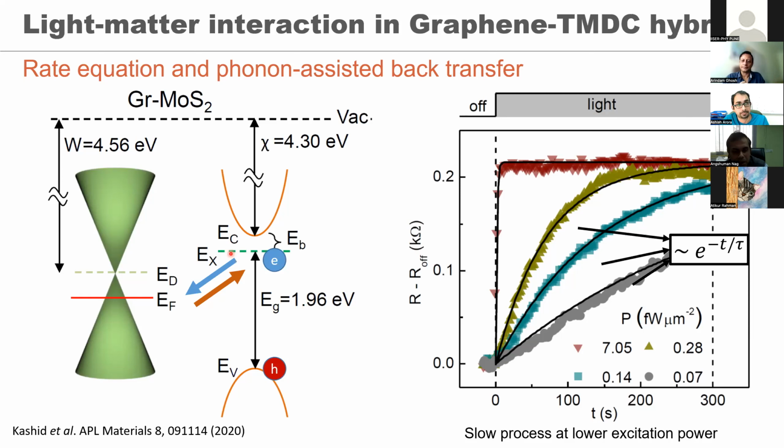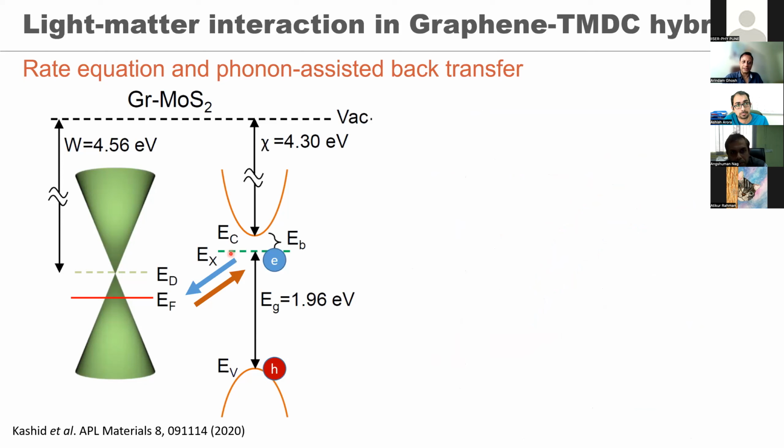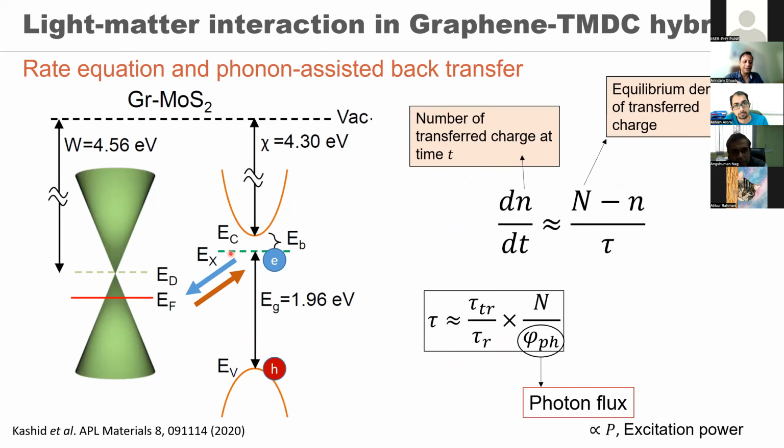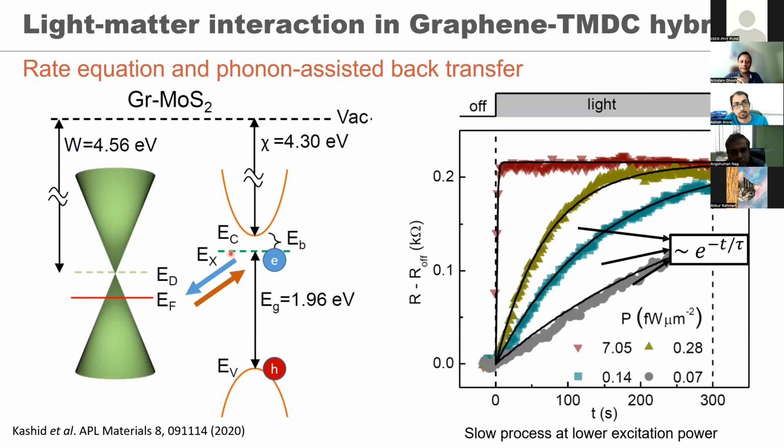Just a clarification here. On this slide, when the electron is transferred very fast, and still you see good enough photoluminescence? Oh, no, you're absolutely right. Photoluminescence strongly quenches. I did not show that data, unfortunately, but it's there somewhere; I didn't want to go into that detail. The moment you have graphene there, the photoluminescence quenches straight away.